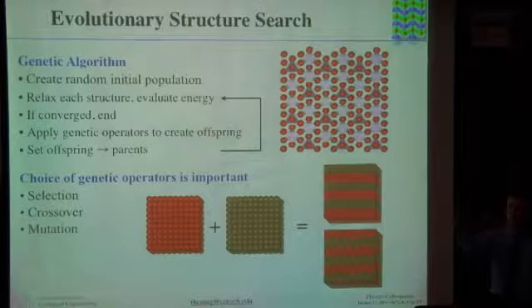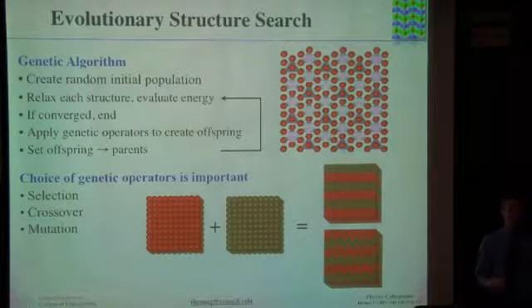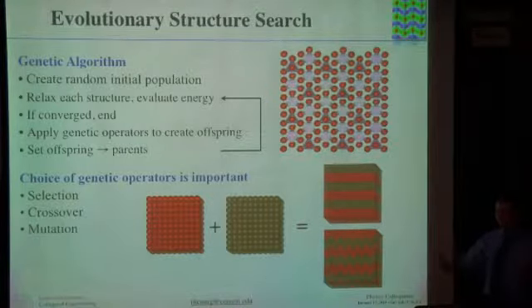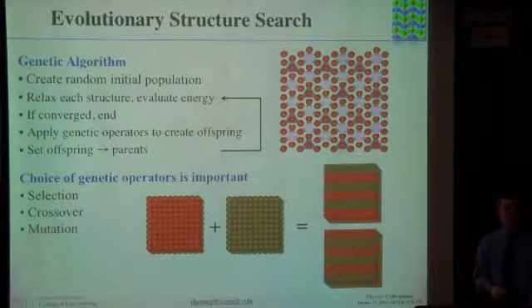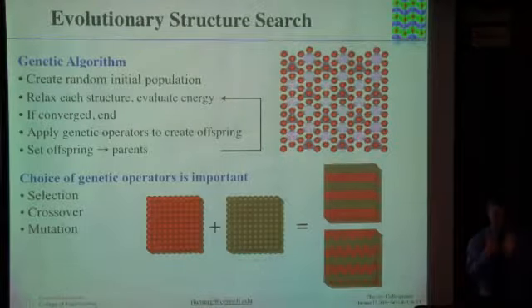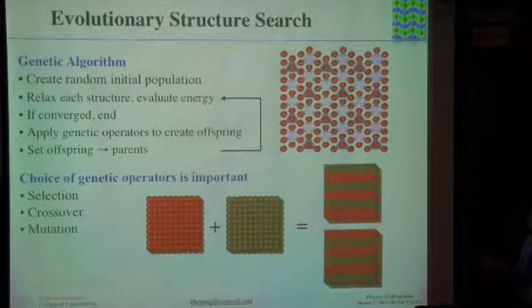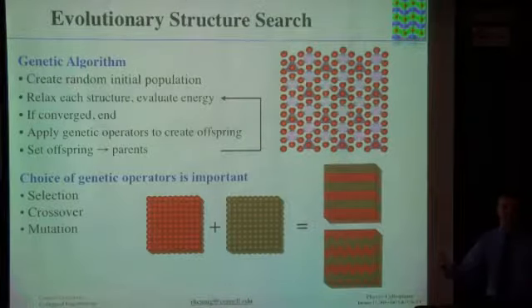We put some constraints on the c over a and b over a ratios to be somewhat realistic. We put some constraints on the angle, because there are symmetries when you go over 120 degrees. That's the same as going to a smaller angle. But they're random. Then we put atoms randomly in the cell. In our case, we also randomly vary the composition, and we randomly vary how many atoms are in the unit cell. We scale the density to be in a reasonable range, because it doesn't make sense to start with something super compressed or super expanded. That's the first step. You end up with a certain number, let's say 20 random structures.